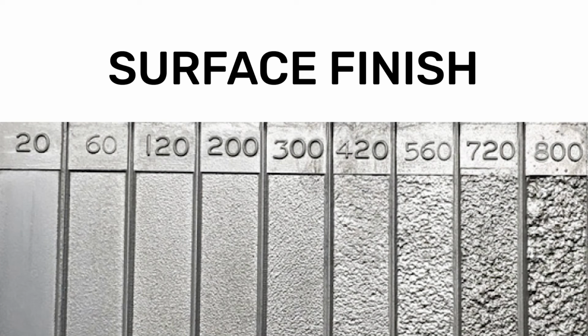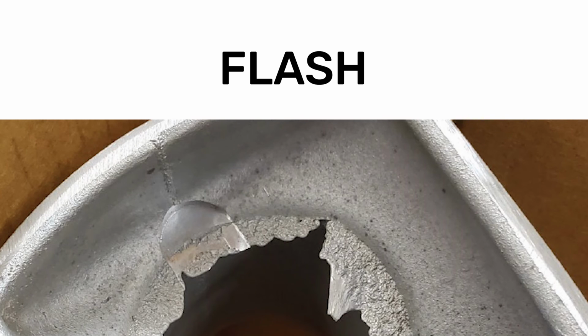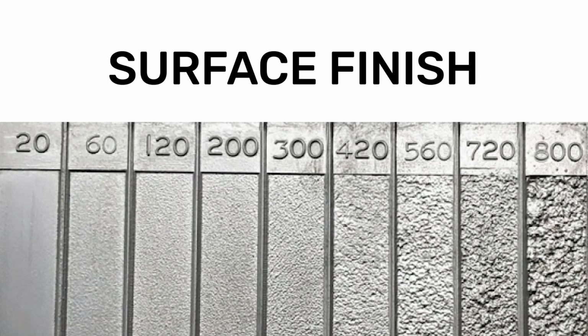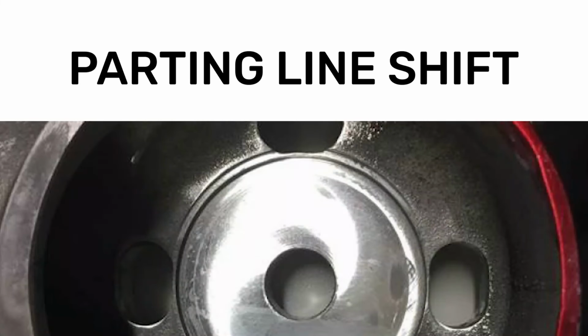One defect we haven't really talked about yet is flash. So flash is when you get these thin little sheets of metal sticking off of your casting. It's caused by metal leaking out of the mold during the pouring process. A little flash is manageable, you can just machine or polish it off, but excessive flash is a telltale sign that your mold is reaching the end of its lifespan. Some other defects that could be caused by poor mold maintenance are rough surface finish, like we talked about earlier, parting line shift, mold misalignment, or even inclusions.